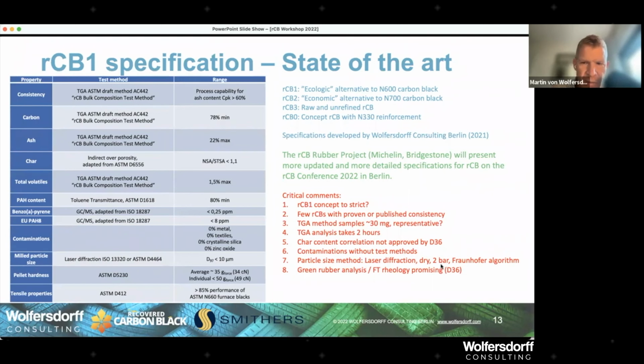So laser diffraction, we need to specify it's a dry laser diffraction, not in the liquid medium. Also, the pressure is very important. Here, the industry standard seems to go into the direction of 2 bar. And also then there's a different algorithm, because the laser rays are diffracted, so they change their course, and the algorithm is calculating the particle size with the assumption that the particle is a sphere. But, as I've shown, neither carbon black nor recovered carbon black are spherical particles. So it's an approximation at best. And there is a work item in the D36 group, which is working on this laser diffraction particle size method. But this is what I defined with the means at hand I had.